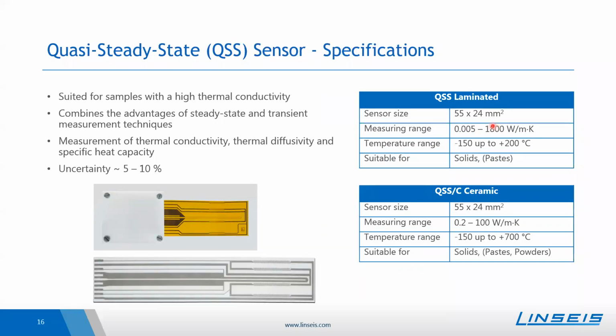The QSS sensor is especially suited for materials with a high thermal conductivity. QSS stands here for quasi-steady state. So the sensor measures a little bit different compared to the transient hot bridge sensor. So here we are not completely in the transient state, but are approaching the steady state. So it's more or less a mixture of the transient and the steady state measurement method. By that, one can combine the advantages of the steady state and transient measurement techniques, which allow then the measurement of the high thermal conductivities. As well as with the THB sensor, one can here determine the thermal conductivity, diffusivity, and also the specific heat capacity.